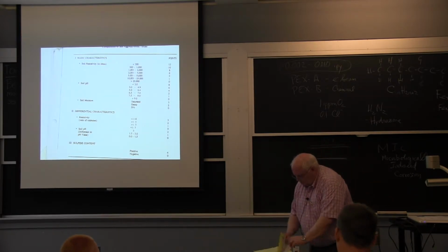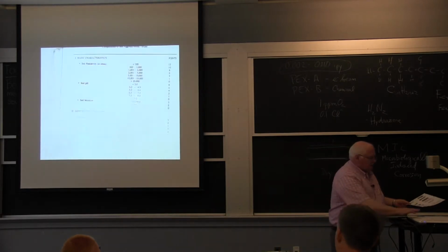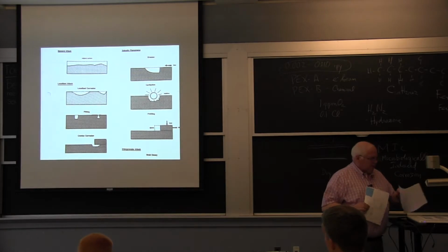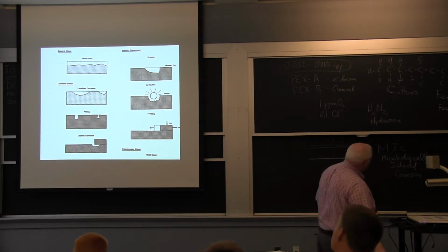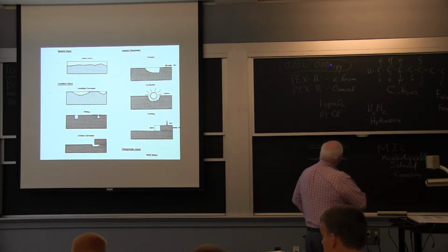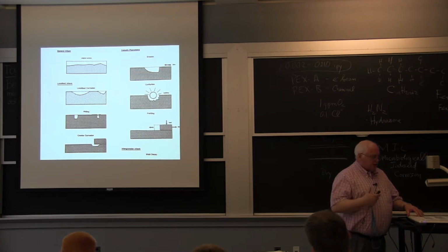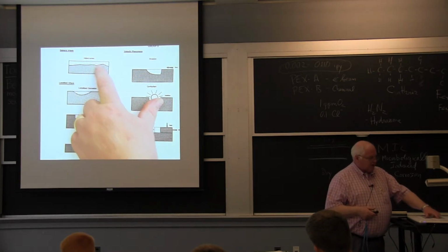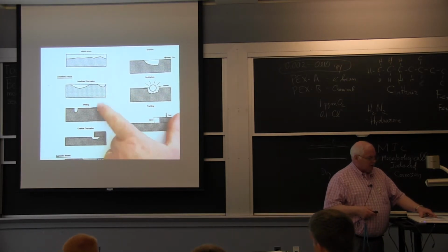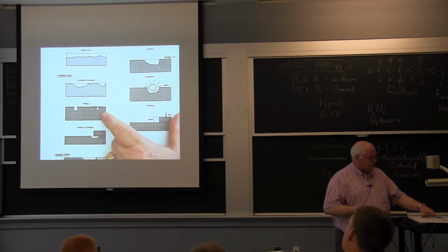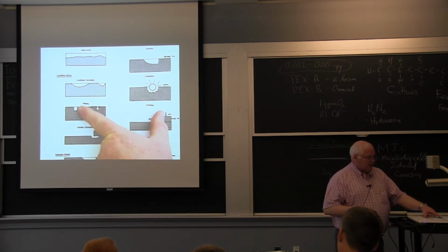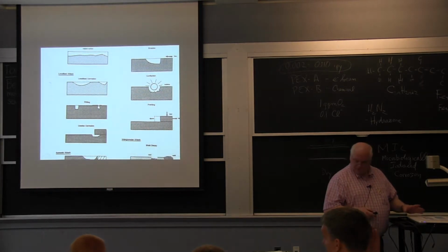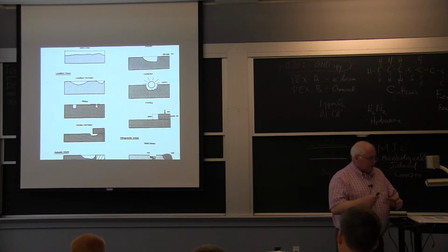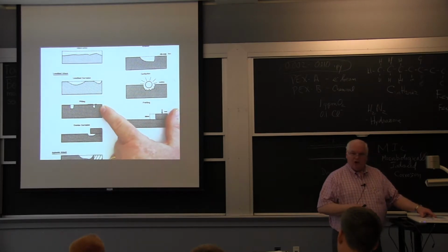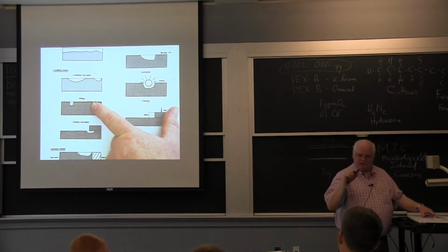Actually, what we've been following, just for your information on some of this stuff, is basically this thing from the forms of corrosion. We talked about general attack earlier today, and we were talking about 0.002 to 0.010 of an inch for carbon steels, and general attack is just a general wasting, rusting everywhere. We talked about localized attack. We talked a little bit about pitting. Pitting is a wearing away of the surface locally, and you get corrosion at a pit. And one of the things I handed out on marine corrosion has a nice little picture of how you get acidic regions and basic regions right around the pit, and they sometimes call it autocatalytic, how that drives the pit. Okay, just boring a hole.